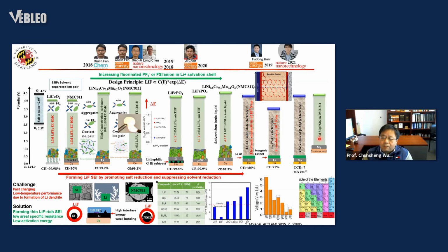Magnesium is even more difficult, because any solvent reduction forms polymer, which will block multivalent magnesium transport. For lithium, if the SEI forms, it still works, it just cannot prevent the dendrite. But for magnesium, you need to really make sure polymer does not form. If you use chloride, it is really corrosive. If you use DME, it will reduce. So we use a new idea.